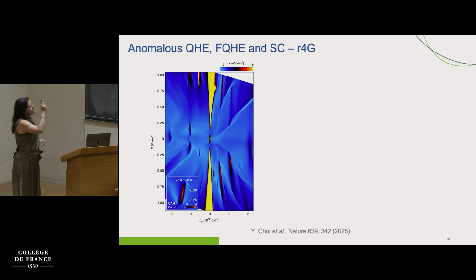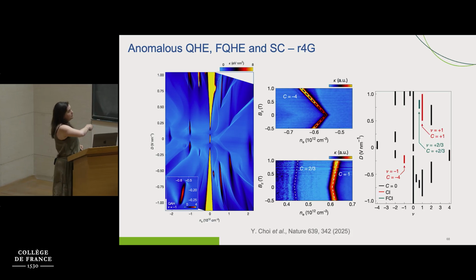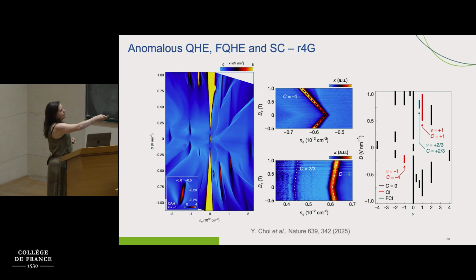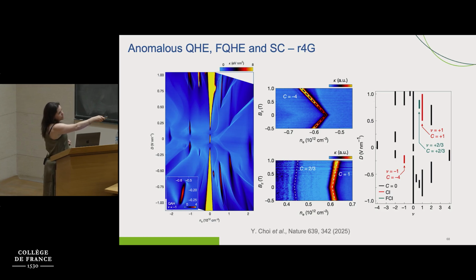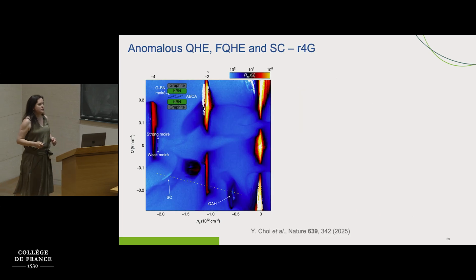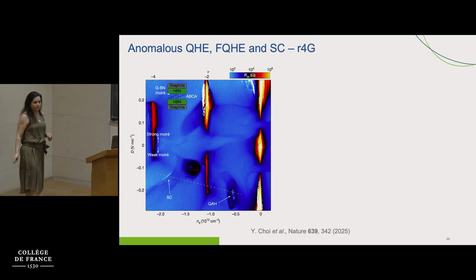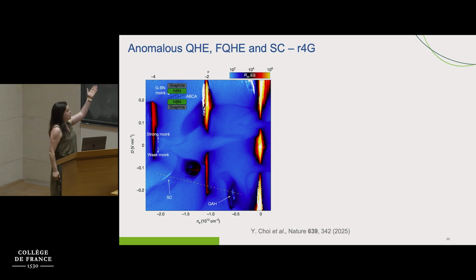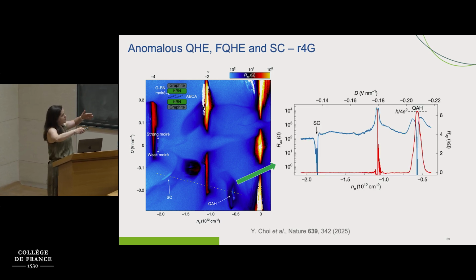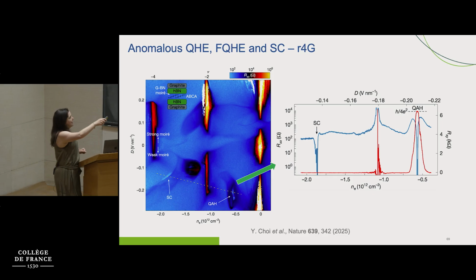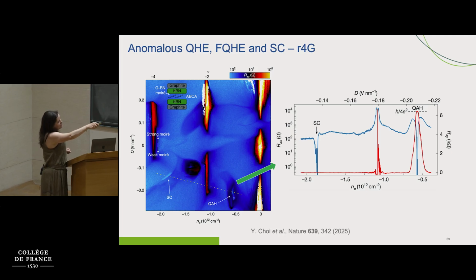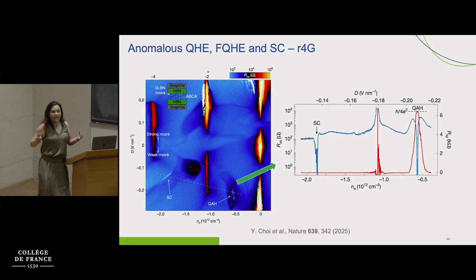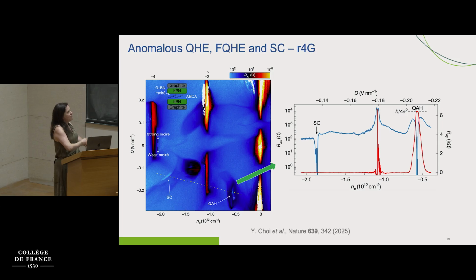So what I want to say here is that for rhombohedral 4 layers graphene, you can still see a full zoology of topological states. Now you have topological states with different Chern numbers, fractions, integers, etc. But you can also see superconductivity pockets in exactly the same system. So this here is what I truly consider to be the most beautiful curve I have ever seen, and I have seen a lot of curves, where you can see superconductivity and quantum anomalous Hall effect in the same device, at the same moment, just by changing the concentration of carriers of the material.